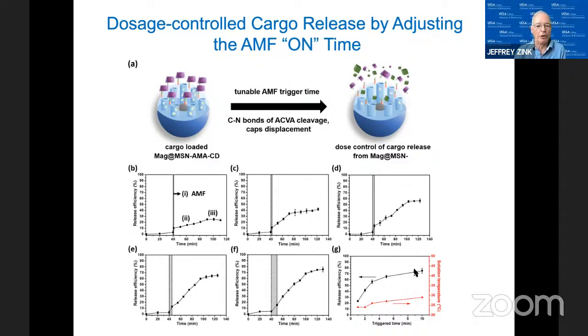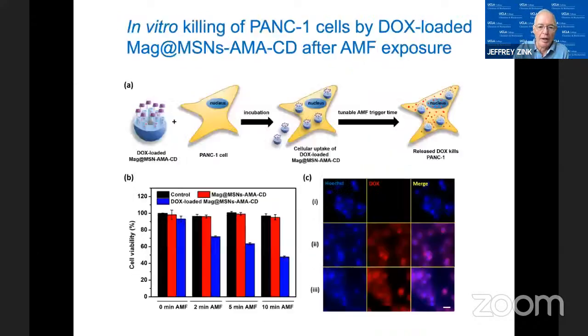So here we're able to control the overall temperature and not damage tissue if we don't want to do it. Of course, if we turn it on longer, we could if we wanted. And we can control the dose. The amount that comes out depends on the amount of time that we've had the magnetic field on. So here we have dose control and drug release by a magnetic field that totally penetrates the system. We've done this in vivo, but we haven't published it yet.